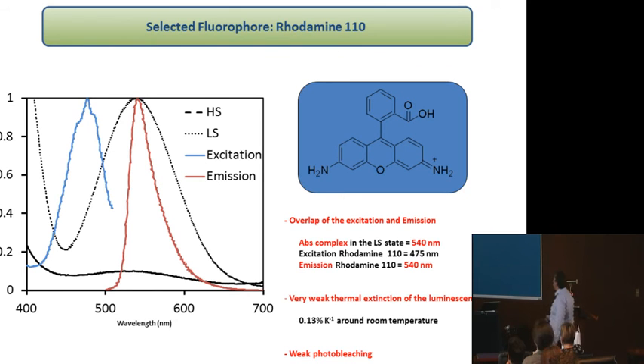Just some details concerning the choice of the fluorophore. We have selected rhodamine 110 because, of course, we have a good overlap between the emission of the fluorophore, in red, and the absorption of the complex in the low spin state. Here you have the high spin state. We also have a very weak thermal extinction of the luminescence for this molecule. This is very important, and also a weak photobleaching. This means destruction of the fluorescent properties.